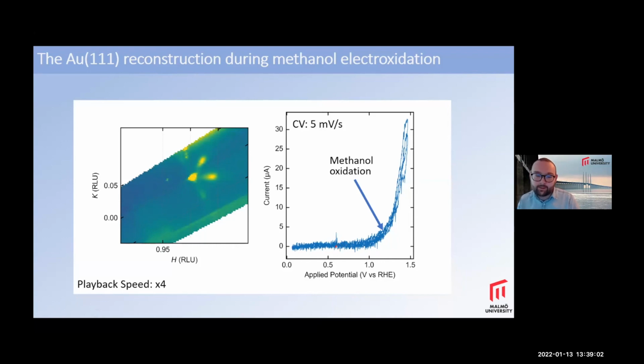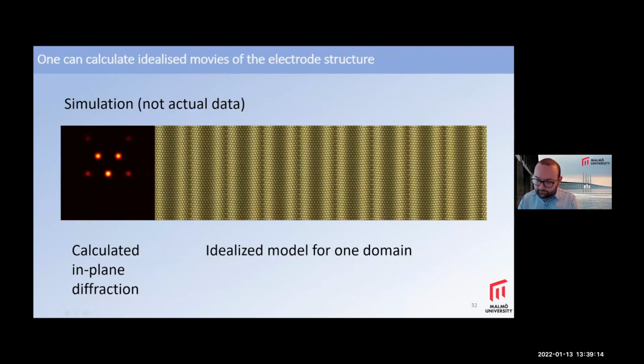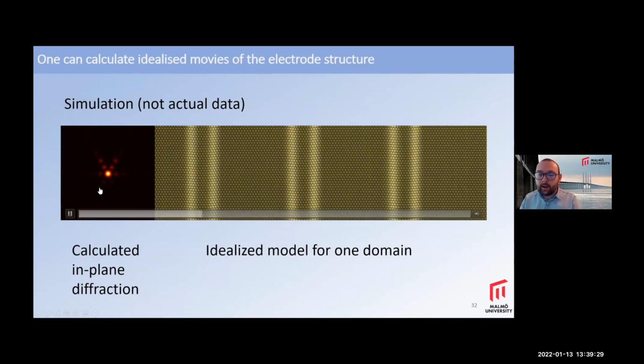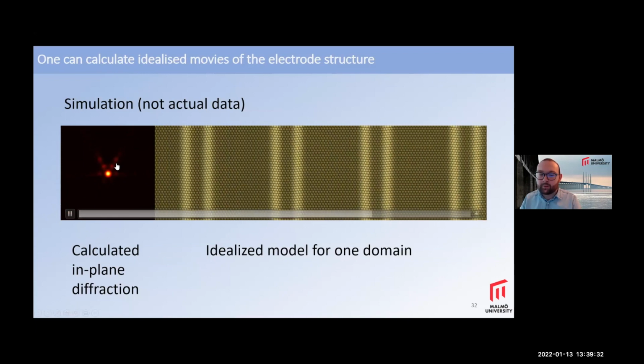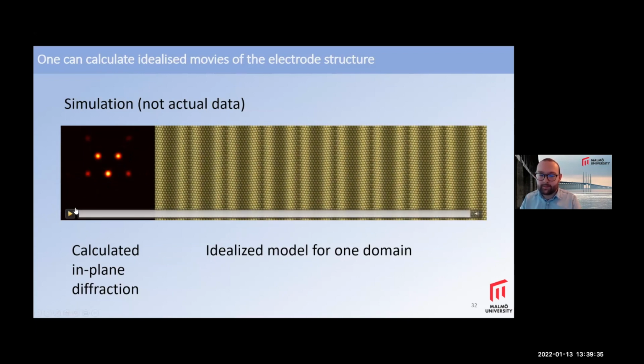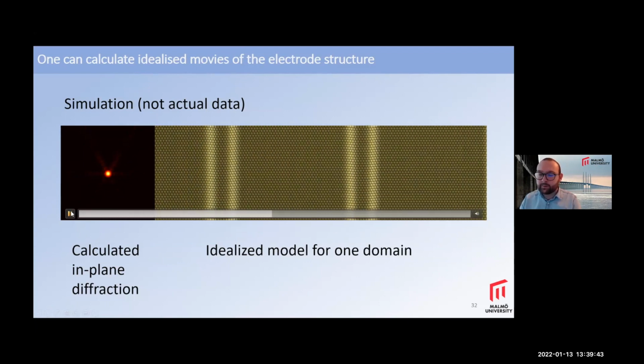And then you can see eventually the surface reconstruction starts to reform at more negative potentials. Okay, but it didn't quite recover fully. We can sort of look at that in this way. So if we simulate what happens when we change the distance between the stripes in this model, we can see that the spots around the CTR move in. So this is a simulated calculation, and that's pretty much what we saw in the real data. So it's sort of this unraveling of the electrode surface.